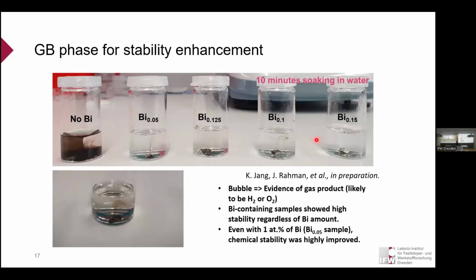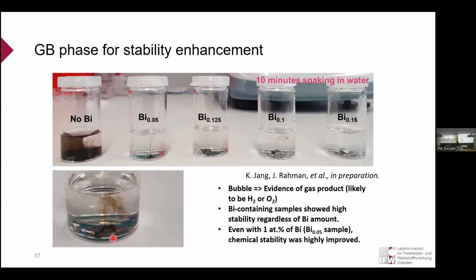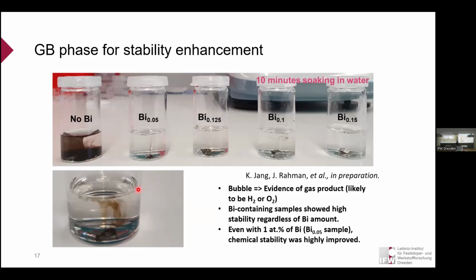Okay, and also somewhat out of expectation, but not surprising, we checked this material after this grain boundary modification. When we don't have this coating, let's say just yttrium telluride, you see this material is reactive with water, and it gradually dissolves into water with some bubble formation. I'm not so sure you can see it, but there are some bubbles forming here. But after we coated this material by bismuth at the grain boundary, the reaction rate has been significantly reduced. And after 10 minutes soaking in water with different concentrations of bismuth, you can see that whenever we have some bismuth here, it's much more stable than the bismuth-free compounds. So this grain boundary coating could also indeed effectively improve the material stability.